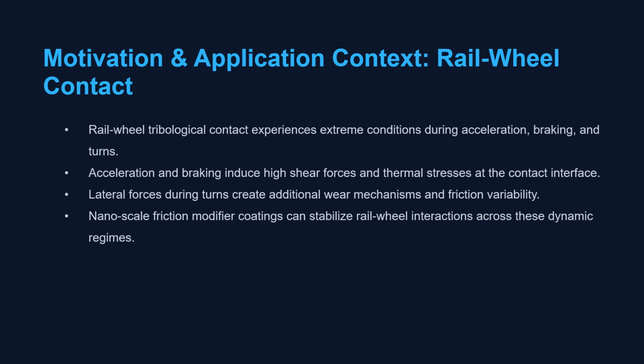The rail wheel interface faces extreme tribological challenges. During acceleration, high shear forces drive the wheel forward. During braking, severe retarding forces and thermal stresses dominate. During turns, lateral forces create additional wear and friction variability that's difficult to control.